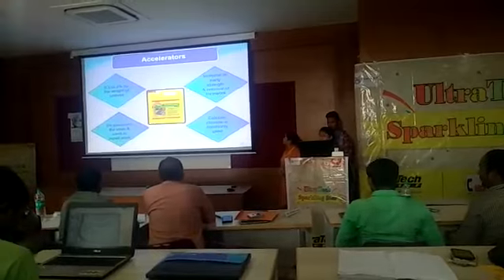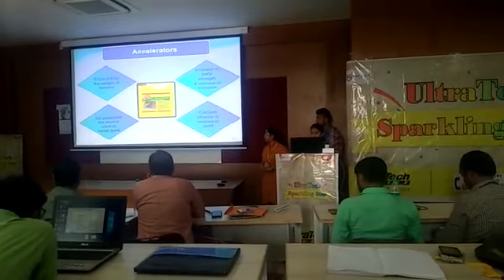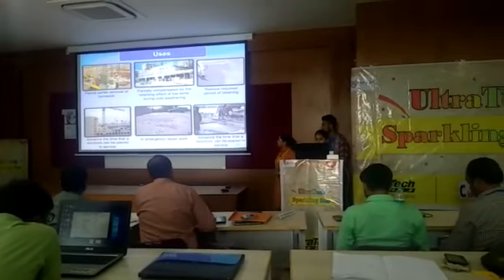Next, accelerators mainly reduce the setting time of concrete. They are useful for early stage development of concrete. Generally used accelerator is calcium chloride, but up to a dosage of 2%. Beyond 2% dosage, it may act as a retarder. Some of its uses are: it permits earlier removal of formwork, advances the time that a structure can be placed in service, and is useful in emergency repair work, in cold weather concreting, and reduces the required period of thawing.